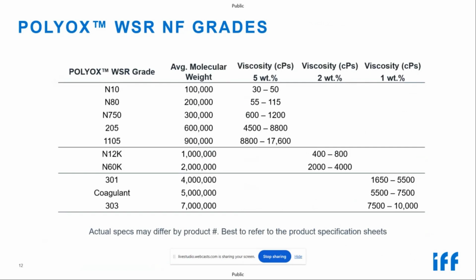This table shows the available polyethylene oxide grades for pharma. The main distinguishing factor is the target average molecular weight, measured using solution viscosity as the specification. The molecular weight ranges from 100,000 up to 7 million Daltons. Due to the viscous nature of PEO, the solution viscosities have to be measured at different concentrations. For the lower molecular weights, that's 5%. For the higher molecular weights, that can either be 2 or 1 weight percent. A subset of these products are offered in fine particle and superfine particle grades.